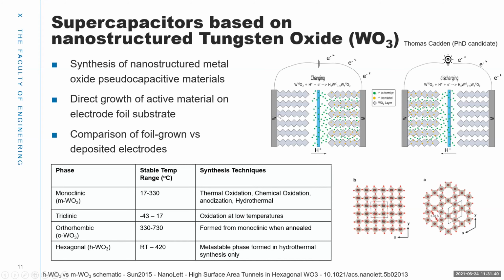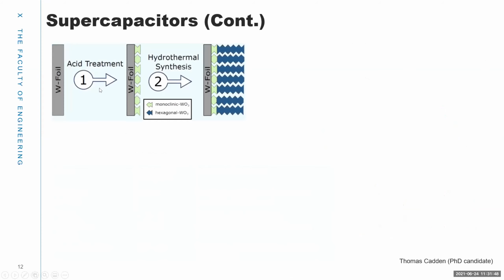And the main aim of this project was to try to grow this material directly on a tungsten foil substrate, because that way, so this is the methodology, we would start with a tungsten foil and we would create a seed layer from acid treatment, and then in a hydrothermal step, we would generate this hexagonal tungsten oxide with a high surface area nanostructure in very few steps. And the idea is that this reduces the number of substrate materials that we need and possibly allows for a cheaper device.